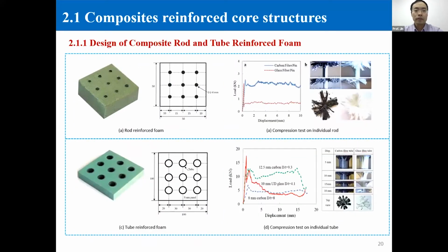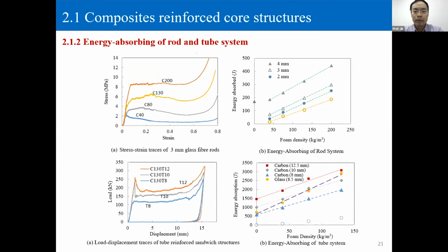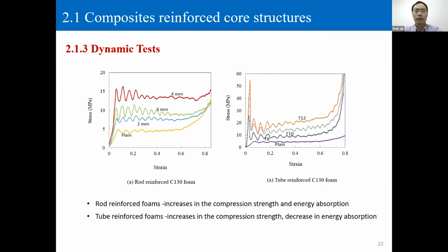Firstly, we did some tests on composite rod and composite tube reinforced foam. That work I completed at Liverpool University with Professor Wesley and Professor Guan, and we found the energy increased with the core density, and we also got the energy absorption chart against the core density, and against the composite rod diameter and the composite tube diameter. Using this chart, we can develop the new structure for applications such as aircraft or high-speed trains.